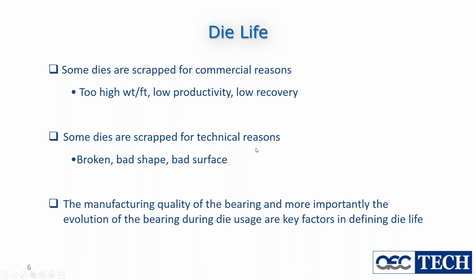Some dies are scrapped for technical reasons. They're broken. If you look at a die plate and you count the number of pieces, and if you get to 2, it's probably broken. That was early advice I had. But we have dies that consistently give bad shape or bad surface due to some defect in the die, and that can also bring the end to a die.